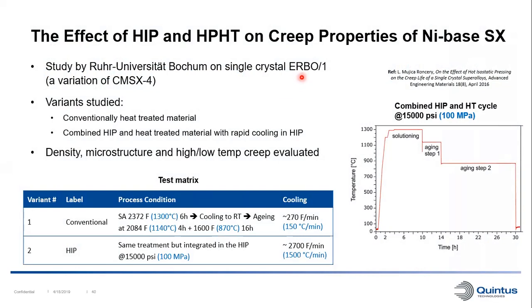And in this study, they looked at two different variants. They looked at material that was heat treated in the conventional way in a vacuum furnace. And then they also looked at the combined HIP and heat treatment step for this material with rapid cooling in the HIP. And then the density, microstructure, and the creep properties were evaluated.